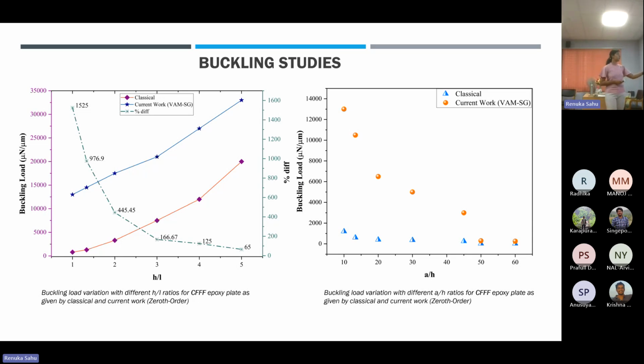As you can see for H by L equals 1, there is a huge difference between the buckling load for the classical case and current case, because it is a smaller structure where taking the effect of strain gradients becomes very important. But if you increase the thickness to 5 times the material length scale parameter, the difference between the classical and current model reduces.